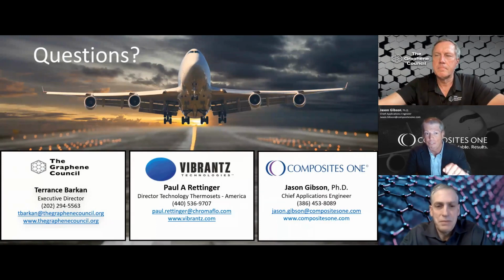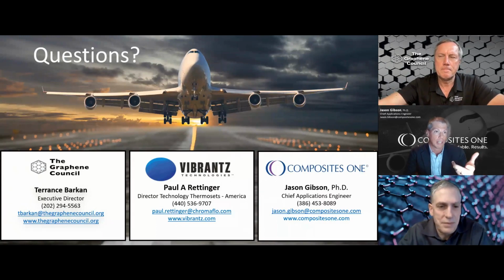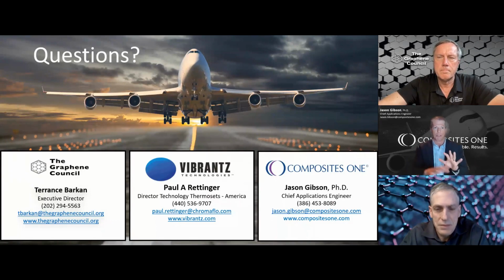Yeah. There's another factor that some people bring up, and that's filtering. Will the graphene be filtered out? Should not. At the size that these particles are at, there is enough porosity in any ply stack that it's able to filter through. If the resin gets through, the graphene will get through. There is no filtering effect because of the size of it. Okay.